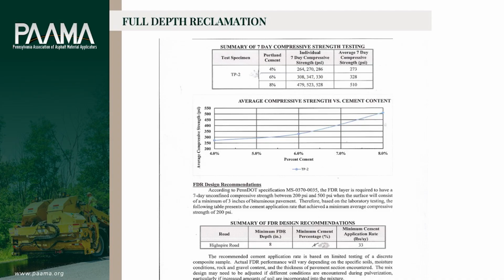But then over to the right there, we have the average compressive strength. See, 273. All right. Then we've got 328, but we've got 510. 510 in a lab is going to produce about 600 pounds per square inch in the field. That's going to crack. Absolutely going to crack. So how do we stop it from cracking?